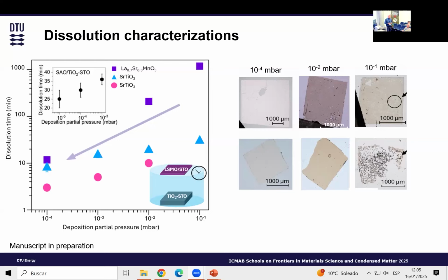So if you increase the number of oxygen vacancies, would the cell parameter of the sacrificial layer change and affect the strain of the upper layers? Yeah, so what you see here is basically the films at different pressures. That's what happened, and it's repeatable. It's not just one or two. We did it a couple of times to see that. So there is a relation between them.